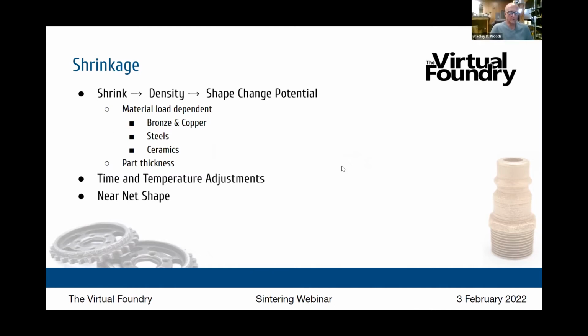Right. So on our side of things, when we make this filament, it's our goal to get as much of the additive into it as we can. So let's stick with copper. In the example of copper filament, we want to get as much metal in there as possible and as little plastic as possible. In the end, the idea is to remove the plastic. So if you have too much plastic and too little copper, you'll wind up with voids and that kind of thing. So essentially what we've done is our recipe and our material loadings are very, very specific, all the way down to the particle size, shape, and the blend of the particle shapes. We've designed this so they all fit together very, very well.